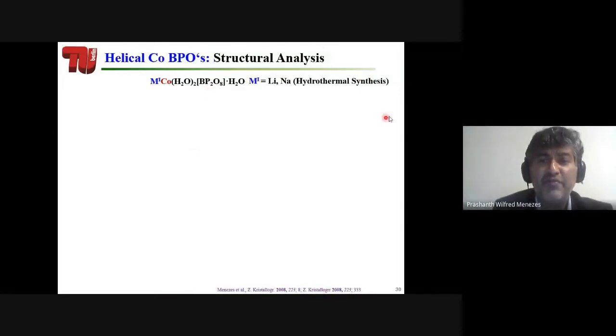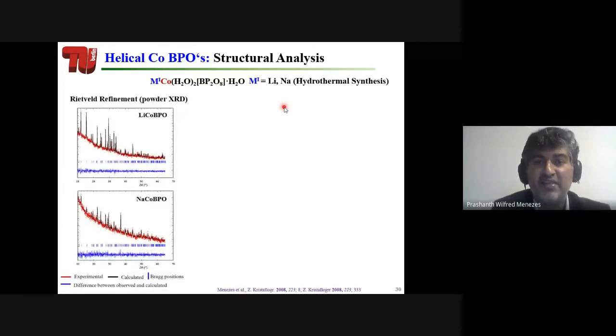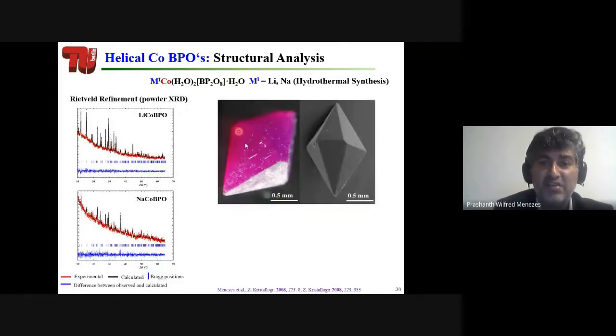How can we produce them? We can produce them from hydrothermal synthesis. That means we can make them under high pressure. You take water, you use all the precursors in an autoclave, and you heat the system. Under pressure and elevated temperature, your precursors dissolve and form nucleated borophosphate, and then slowly they grow, and then they form nice single crystals. The picture of single crystals is shown here.